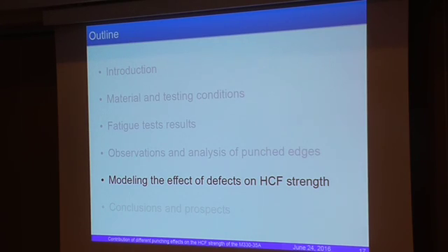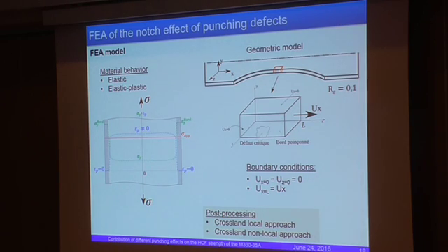So I will say a word about how we model geometrical defects. We made some finite element calculations on elementary volumes around the critical defects. Of course, we don't know the cyclic behavior of the 200 micron deep hardened layer. So we use two different hypotheses. Either the hardening is very large, so we may assume the material remains elastic, or there is no hardening, and then we use the macroscopic cyclic behavior of the material. And we did our calculations and assessed a Crossland criterion.